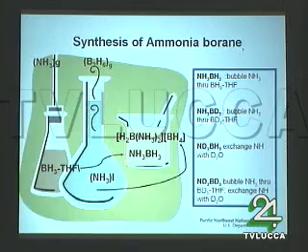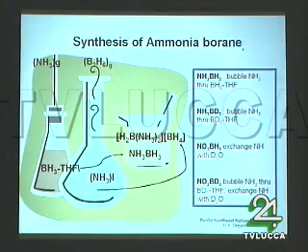So here's my cartoon slide. Here's a physical organic chemist's approach to synthesis. The ammonia borane itself could be synthesized quite easily. There are other ways to do it, but if we want to get the deuterium incorporation in here, the simplest way is to bubble ammonia through a BH3 etherate solution, then with excess ammonia, remove the solvent when you're done, and you have ammonia borane. A very clean, pure way of making it.